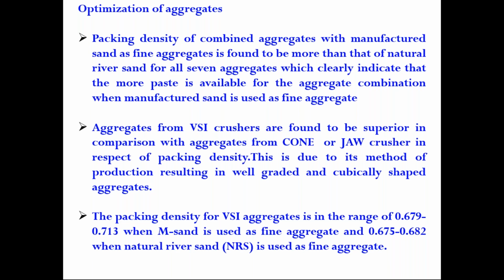That means there is a better packing density. So when the packing density is more, the volume of paste required is less. So when you are fixing the minimum paste content, you are left with more paste volume so that your workability and strength requirements are taken care of. Aggregates from VSI crushers are found to be superior in comparison with aggregates from cone and jaw crushers in respect of packing density. This is due to the method of production, resulting in well-graded, cubically shaped aggregates. The packing density for VSI crushers is in the range of about 0.679 to 0.713.